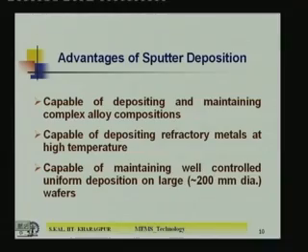In sputtered deposition, if the target has a fixed stoichiometric ratio composition, the deposited film will more or less have that composition — though not exactly, as it depends on the yield of individual components in the alloy. But you will have better alloy composition control compared to electron beam or resistive heating simultaneous evaporation techniques, where controlling stoichiometric ratio is difficult.